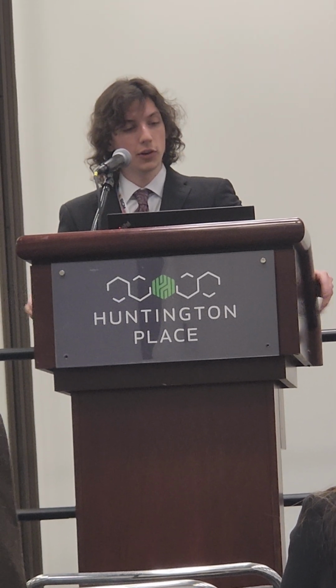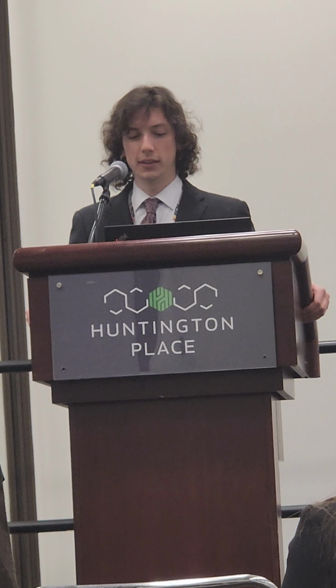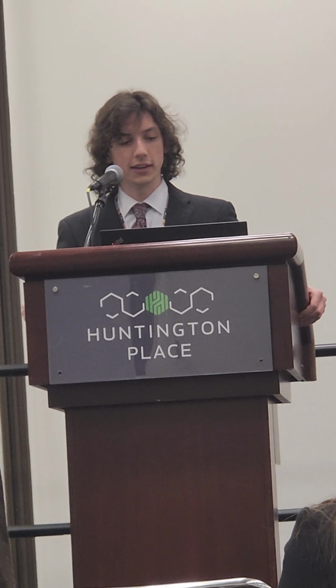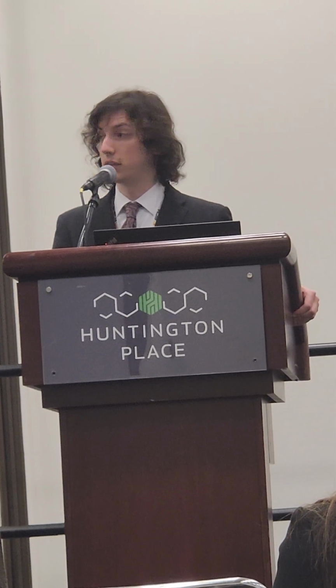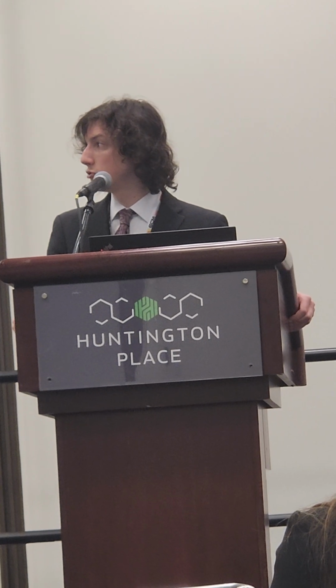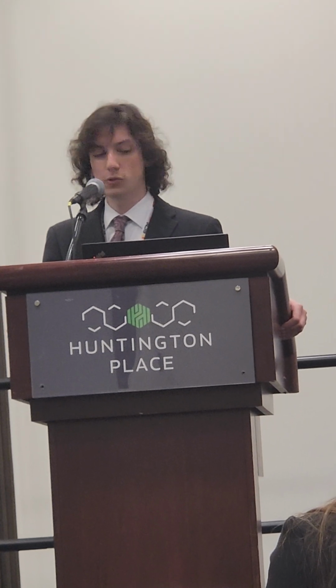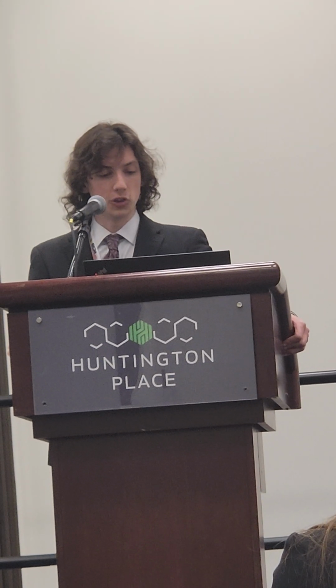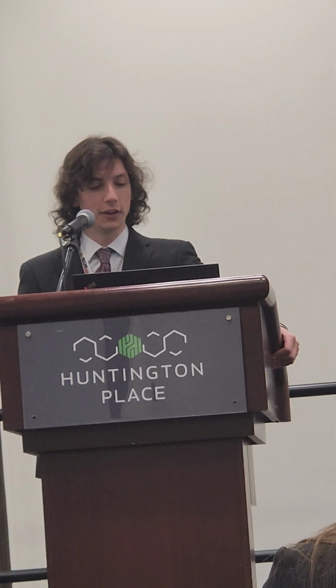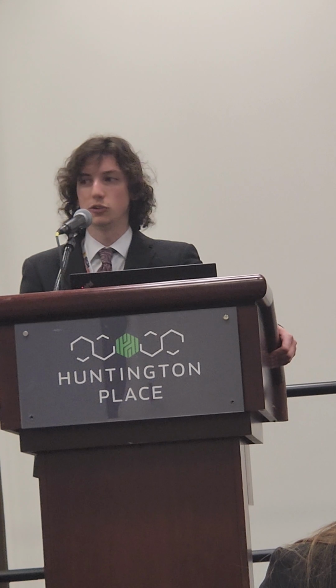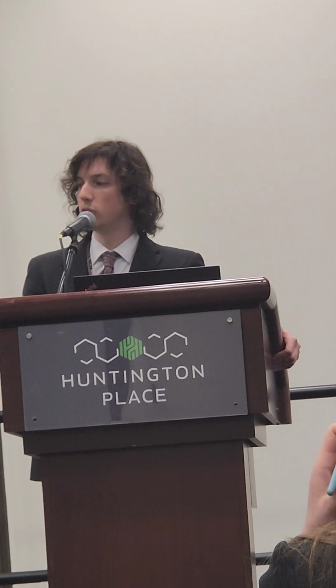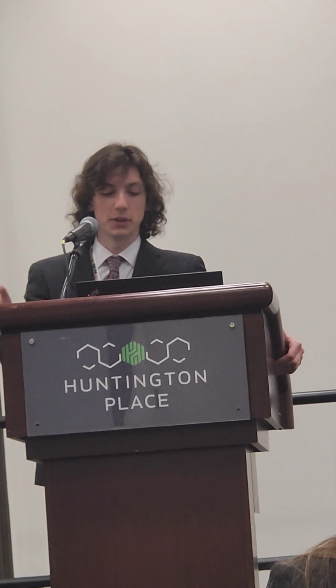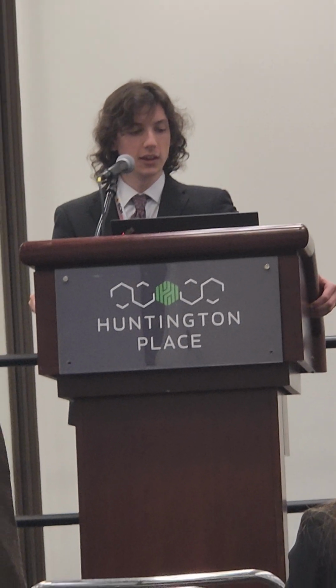Now, regarding abnormal grain growth, any abnormal grains in this or Lee's work are defined as having a diameter equal to or greater than 30 microns. So the abnormal grain growth is normalized by the total grain area. So this is the total area of abnormal grains divided by the total area of grains measured in general, which we could do with the total measurement of intercepts of all the grains.